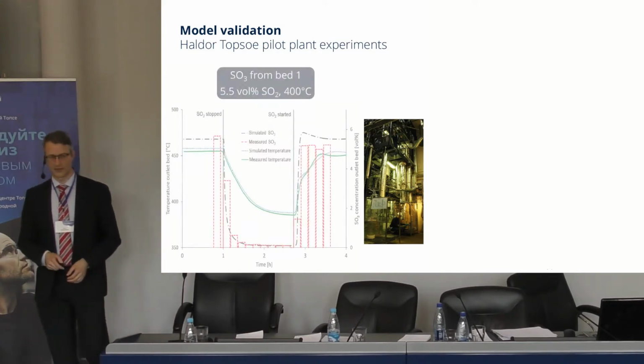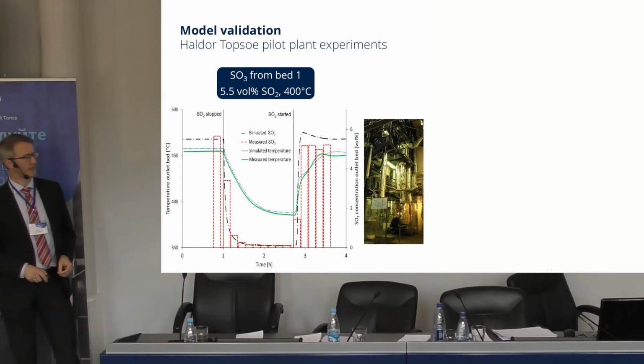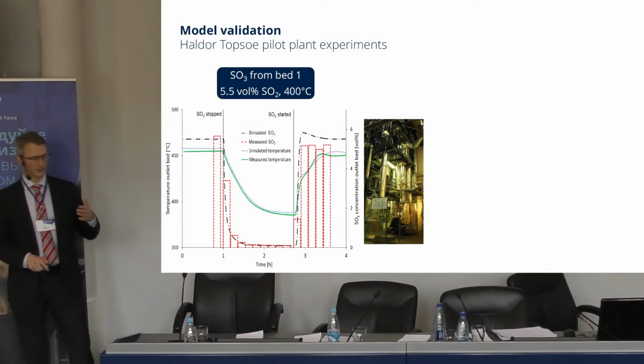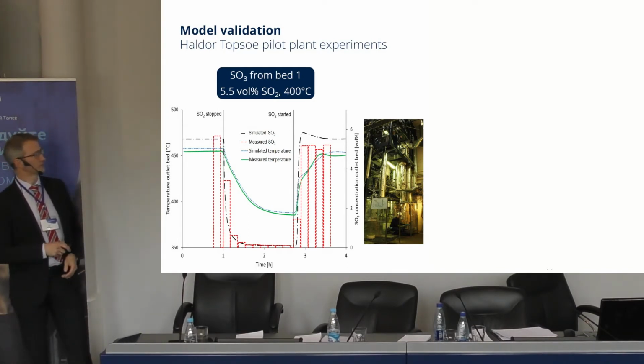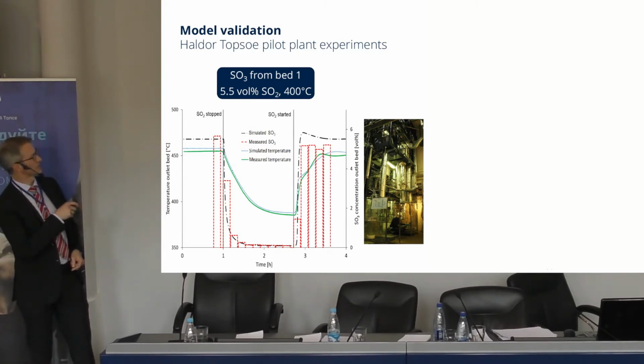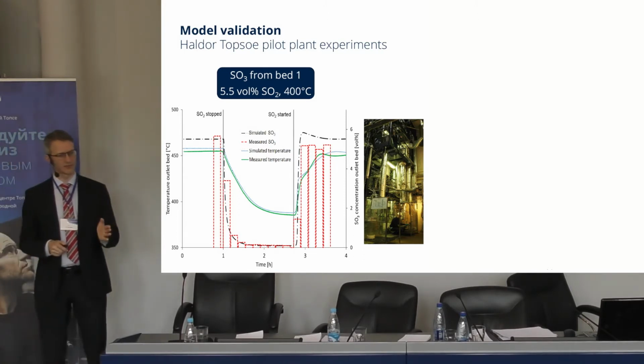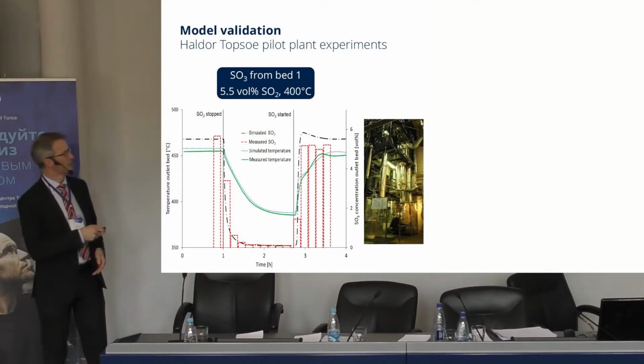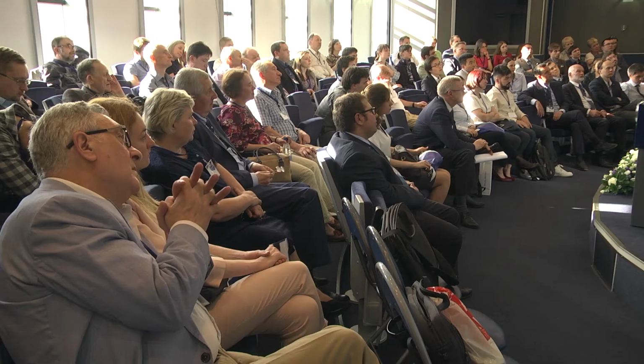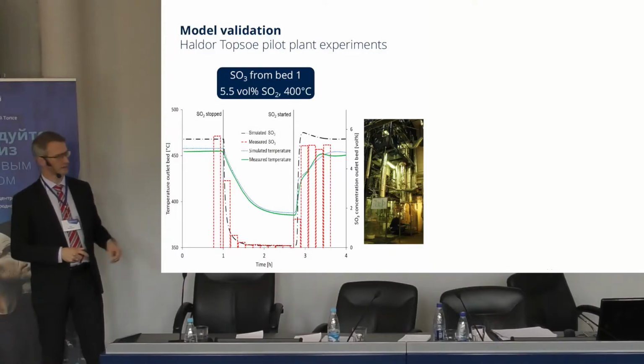One example on the left is how the SO3 is out of bed 1 when the SO2 is shut off. So we run steady state until this point, then we stop the SO2 feed. We still have nitrogen and oxygen going through, so we have the full gas volume, but no SO2 in there. And then we start the SO2 again here. You can see temperature drops. That's the green and blue one, one calculated, one measured. And then when we start up again, temperature rises again. That's well modeled in this case.